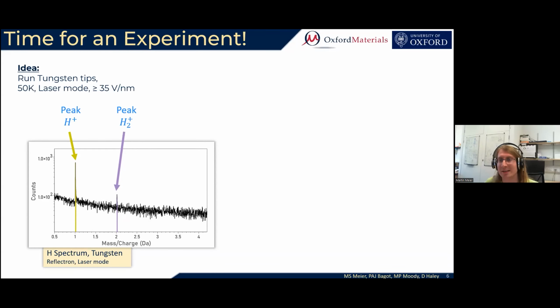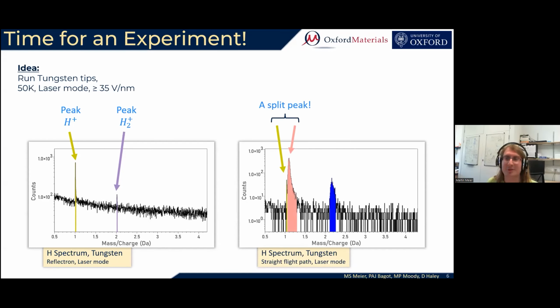But it's also not really interesting, is it? There's something more interesting that we could do, and this is repeat that entire thing on a straight flight path machine. And what we see in this experiment is that the H+ peak is turning into a split peak. So there is now one part of the peak that is just at the mass-to-charge ratio where we expected, and a second relatively large part that we detected at an unusually high mass-to-charge ratio. And this is down to an energy deficit.